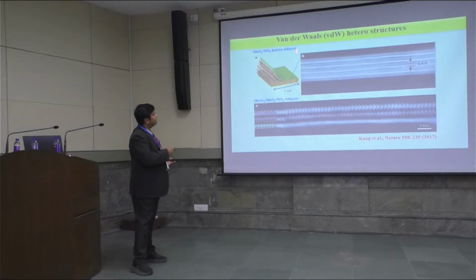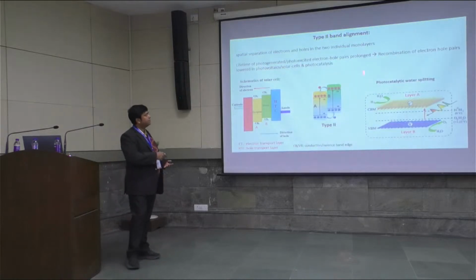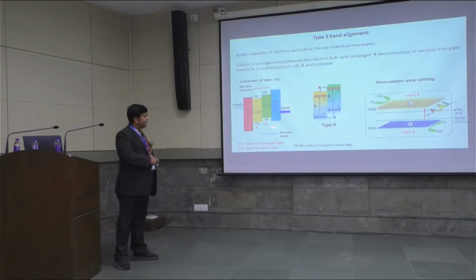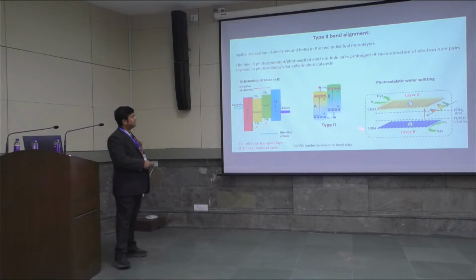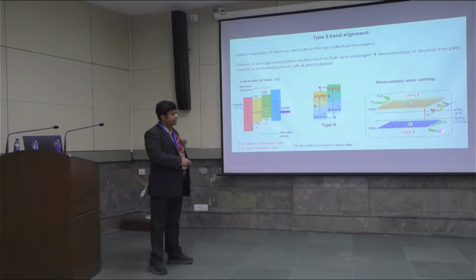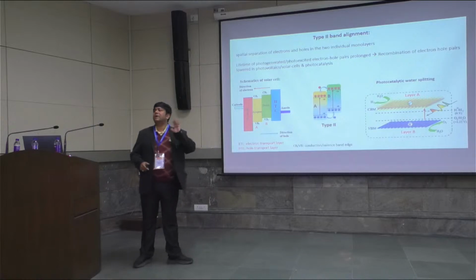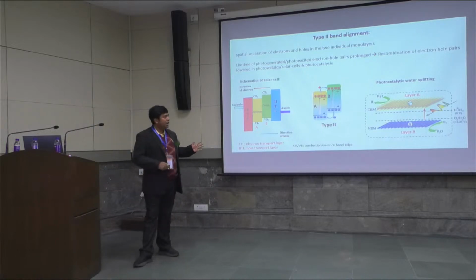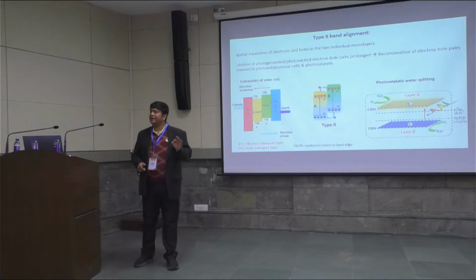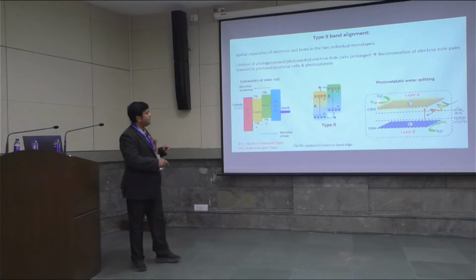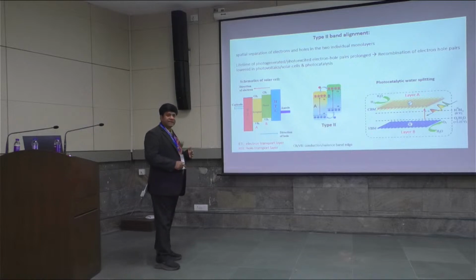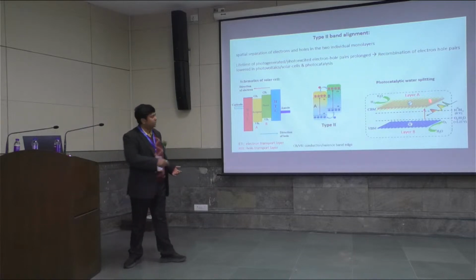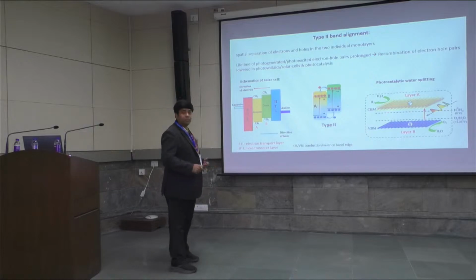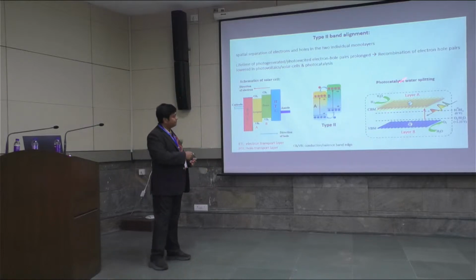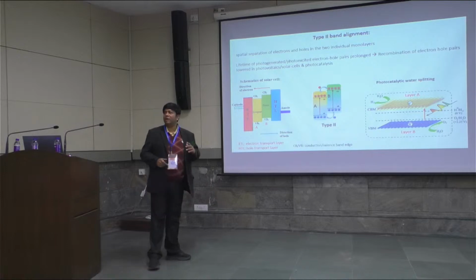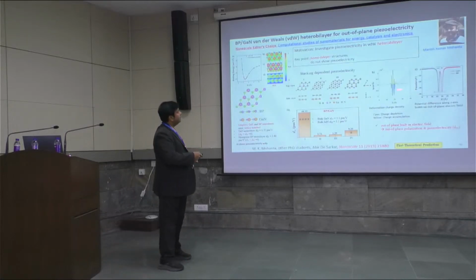So it's time to switch gears to van der Waals heterostructures. Van der Waals heterostructures have mainly been studied in light harvesting applications, for example in photovoltaics and in photocatalysis. Because of the type 2 band alignment, the electron-hole pairs can be spatially separated in the two individual monolayers. Now, as Professor Pandey mentioned in the morning, interface-driven properties were overlooked. Say, for example, piezoelectricity which might arise from interface effects or from interfacial polarization was completely overlooked in van der Waals heterostructures until we predicted it for the first time in this paper.